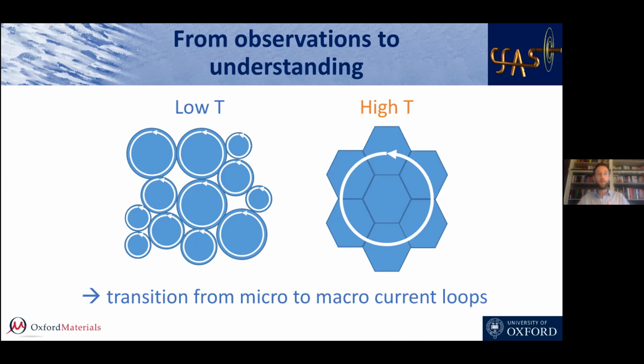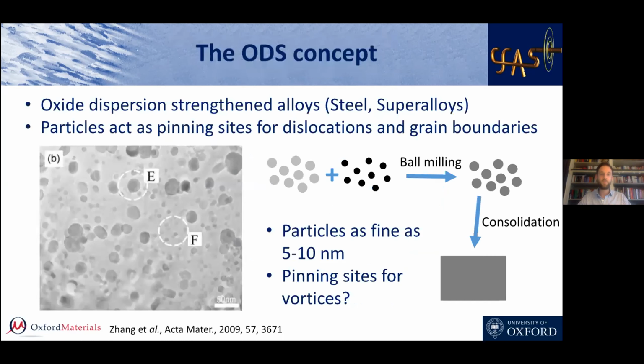And when we understood how those simple parameters worked with pure MgB2, we could add a level of complexity to the system. And here I'm going to introduce a concept, which is the oxide dispersion strengthening concept. In alloys like steel and superalloys, metallurgists have done for 40 years something which is very simple: taking a metal and putting tiny oxides in it, oxides that can be as fine as 5 to 10 nanometers.